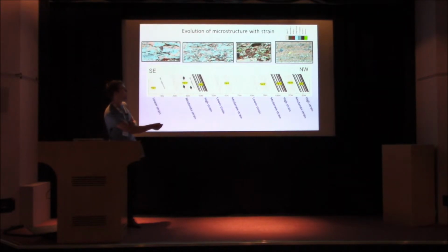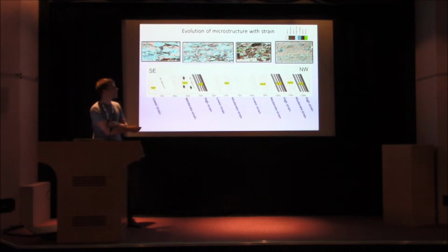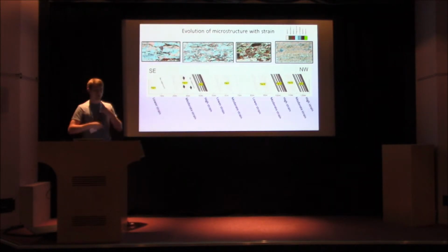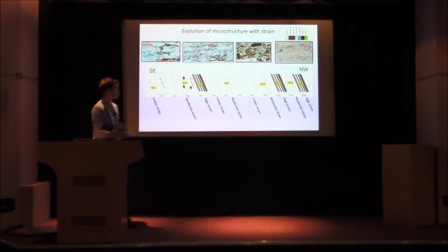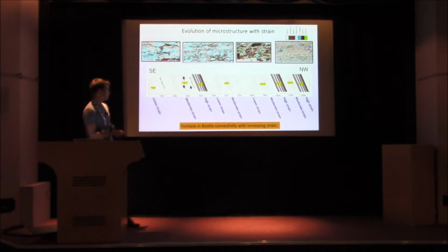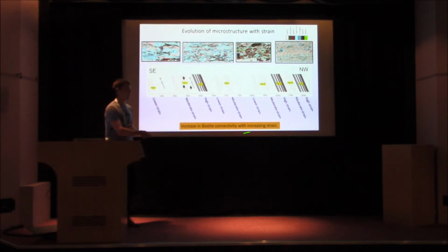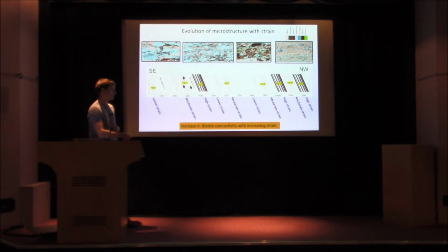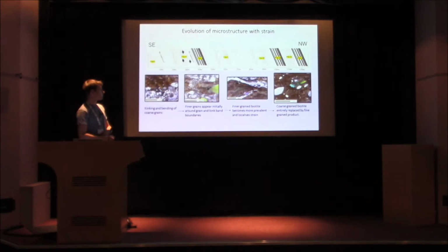And the reason you can't see much red and green there is because it's very, very fine, and it's interconnected into like a big matrix. So the whole thing is quite well mixed. So what you're doing is you're connecting the weak phase, as I was describing, and you're concentrating more and more strain into mica. So there's an increase in biotite, particularly biotite is a type of mica, connectivity with increasing strain.